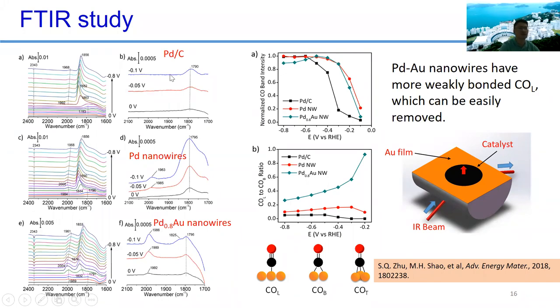Okay, so we did the in situ FTIR study, but this time it is not a metal film, but instead the real nanoparticle and nanowire electrocatalyst. So we first deposited a gold thin film and then coated the gold thin film with the catalyst. Now we can use the gold film to increase the connectivity, so we can do the in situ measurement.